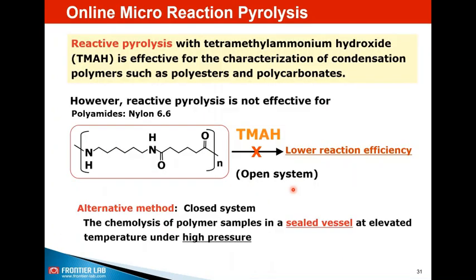Okay, so here, since we are dealing with polymers, we are showing an application on polymers. I said generally reactive pyrolysis with tetramethylammonium hydroxide may be sufficient for polyesters or polycarbonate. But in the case of polyamides like nylon 6,6, the open system does not give sufficient efficiency. So one has to go for an alternate method like a closed system, which is basically the micro reaction. As I said, here the sample is heated in a closed condition, which helps develop high pressure also.